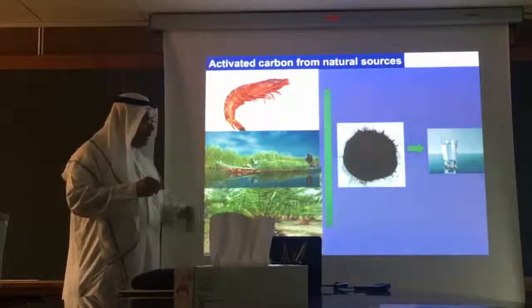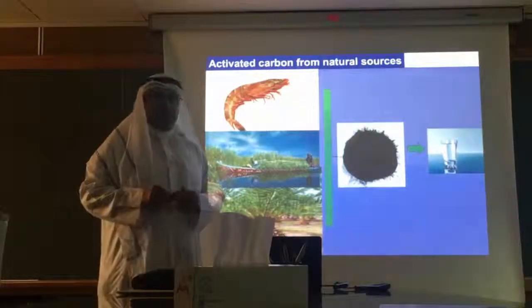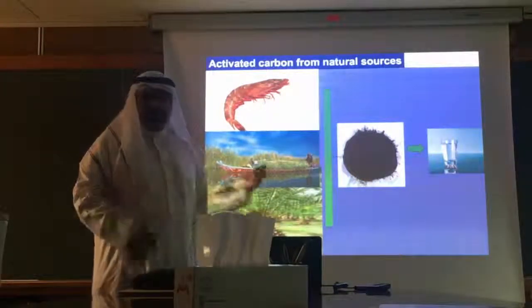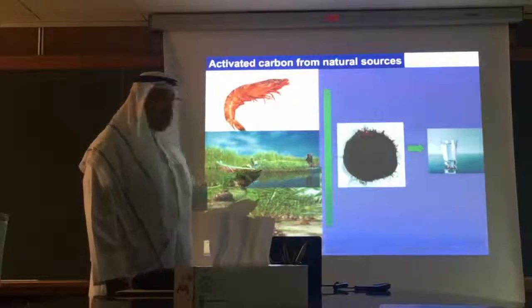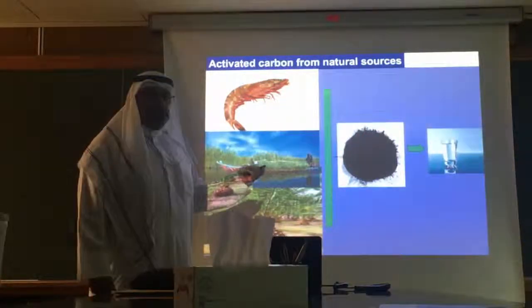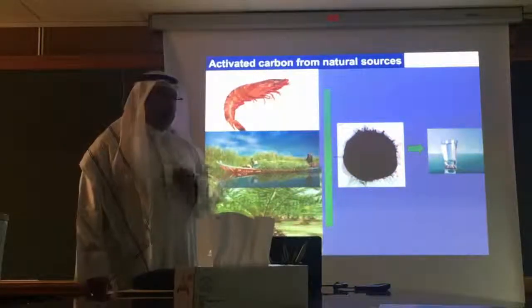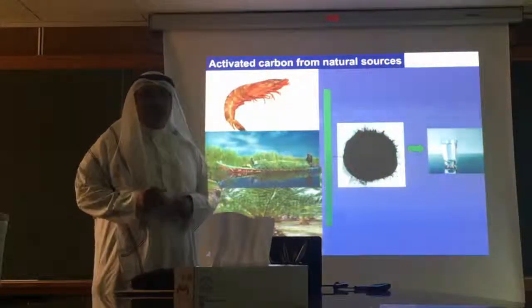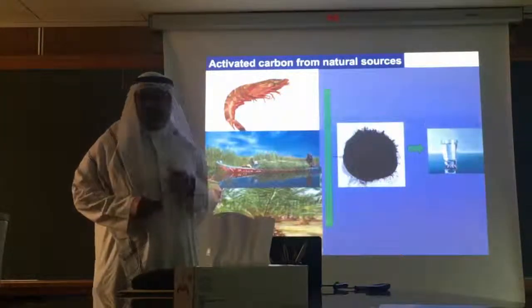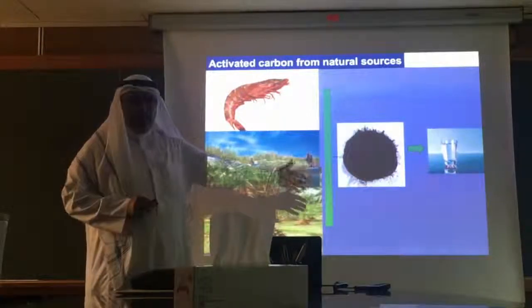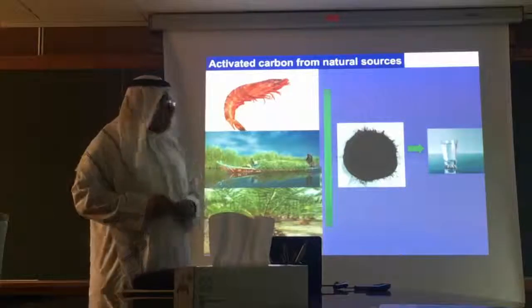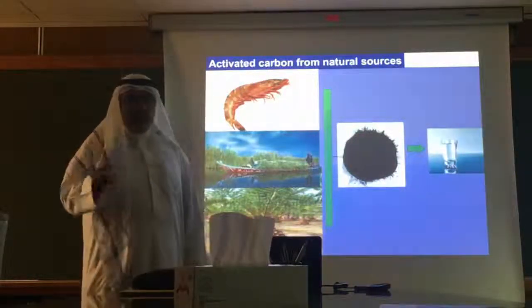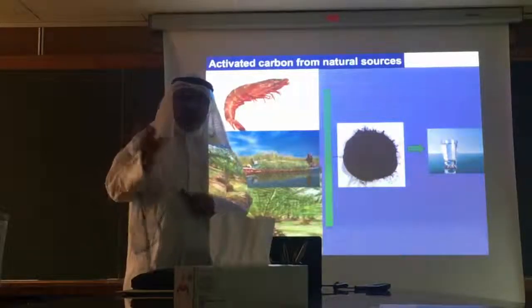This is very basic, and much research has been done in this field. But in my work, I try to increase the percent of nitrogen in the charcoal. This is very, very important. The highest nitrogen content you can get in charcoal so far is 9% or around 10%. If you can enhance it to 15% or 20%, this will make a huge difference in water purification. So my main research is controlling the enrichment of the charcoal by nitrogen with different chemical methods. Of course, after we prepare it from natural bio waste, we enrich it with nitrogen, and then we test it for water purification from heavy metals, for example, because the nitrogen has a lone pair that will catch the impurities, especially the heavy metals.